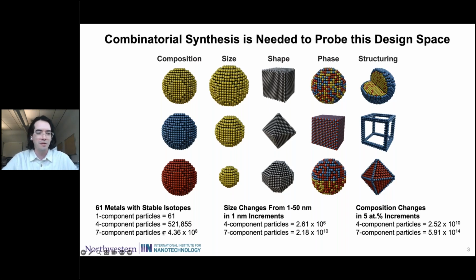And just to look at some numbers, if you're thinking about a metallic nanoparticle, we have 61 metals with stable isotopes that we can put together. If you go up to mixing 7 elements together, you already have 10^8 possible combinations. If you then start introducing size changes, 1 nanometer size changes, you're jumping up to 10^10 possible compositions. Then changing the ratio among those elements, you're expanding all the way to 10^14. So it's a scale of materials design that's really not accessible by traditional methods.